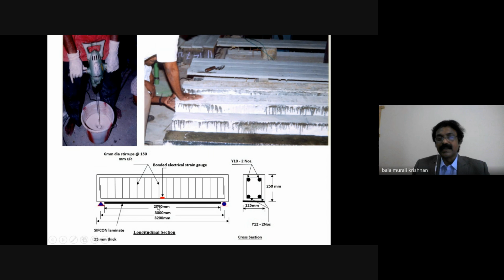If your bonding is good, there will be no issue. It acts as a composite material. I told earlier, two or more elements of different materials act together and carry the load. Here, there are two materials, one is the beam, another is the laminate. The two are bonded with the epoxy resin. With the flexible epoxy system, up to the load spectrum, there will be no bond failure. Till the end, we are achieving compositeness. Once compositeness is lost, nothing will happen and we are not able to achieve the target. So the resin is very, very important to achieve compositeness. In our case, up to ultimate load, there was no delamination or debonding. That's why the results were very successful.